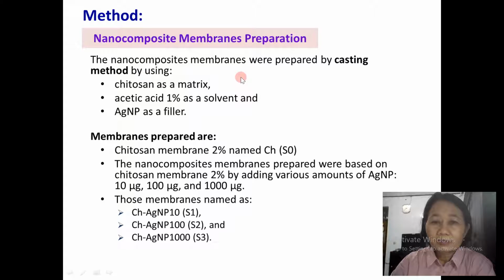The nanocomposite membranes were prepared by casting method, using chitosan as a matrix, acetic acid 1% as a solvent, and silver nanoparticle as a filler. Membranes prepared are chitosan membrane 2%, which means pure chitosan membrane, that we call S0, and the nanocomposite membranes prepared were based on chitosan membrane 2% by adding various amounts of silver nanoparticles such as 10 microgram, 100 and 1000 microgram. Those membranes are named S1 for chitosan membrane with nanoparticle 10 microgram, and then continue S2 and S3.